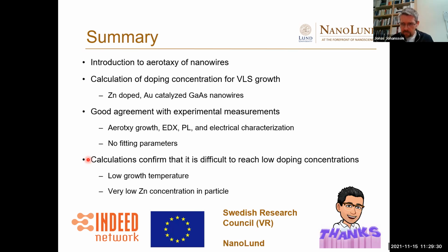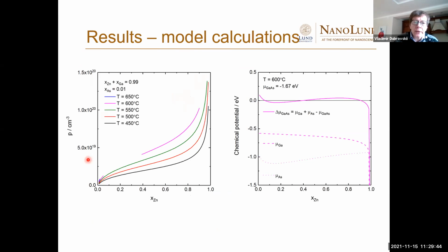So you mentioned some cases where you couldn't grow nanowires after adding zinc. Yeah, there were some, because it modifies the chemical potential difference. Yes, but my question is, you mentioned at the beginning this growth model where the nanowire growth rate can be either group 3 limited, group 5 limited, or incorporation limited. When you add zinc for doping, can it also change the growth regime from transport limited to incorporation limited, for instance? Do you observe that?